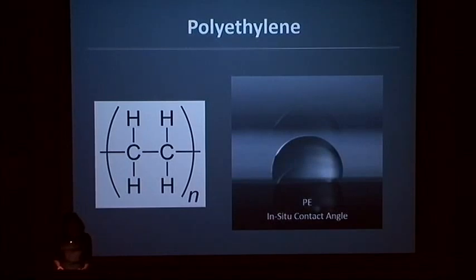This is the crux of the problem for RC prints in general. Adhesives that have a very good cohesive strength arising from their own polarity have a weak affinity for non-polar material like polyethylene. Wetting is the first step towards adhesion. Consider the long-term ramification of a bond between two materials that have a weak affinity for each other. If the substrate was more polar, however, like polyester or even an oxidized polyethylene, the water would more effectively wet the surface. We can quantify the difference with contact angle measurements, which we will show in a few slides.